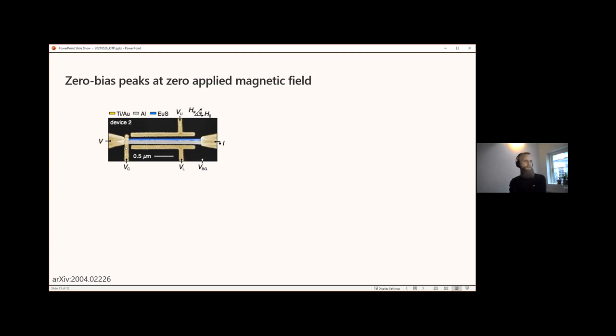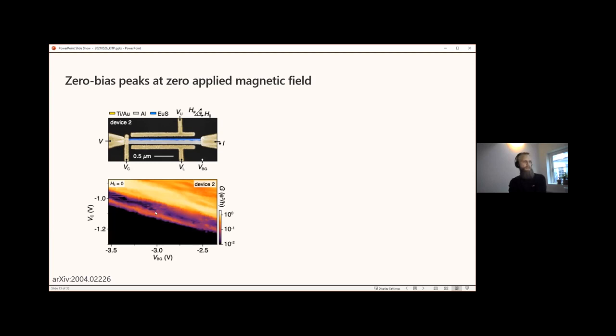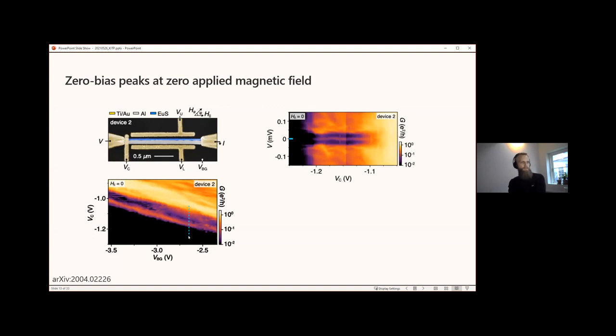to the lead. If you take a conductance map for the device as a function of cutter voltage and the back gate, we see that there's a crosstalk between the two gates, but essentially the device can be pinched off around 1 volt or so. Taking a cut for this specific gate voltage and back gate as a function of cutter, we see that as a function of source drain voltage, we see the conductance from open regime through tunneling into the pinched off regime. In the open regime, the device displays Andreev enhanced reflection, and in the pinch off regime, the transport is